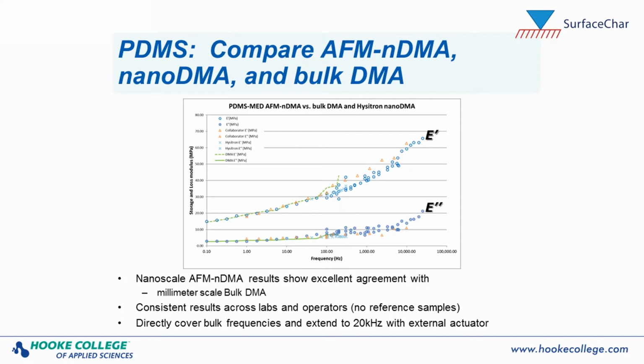So we can compare the results of AFM nano DMA with bulk DMA. There's another nanoscale DMA measurement called nano DMA, which is on a slightly larger scale, more like hundreds of nanometers localization. That's by an instrumented nanoindenter. And so we can compare the viscoelastic measurements by all these three techniques on PDMS. And so here what we have is a plot of the storage modulus and the loss modulus on PDMS